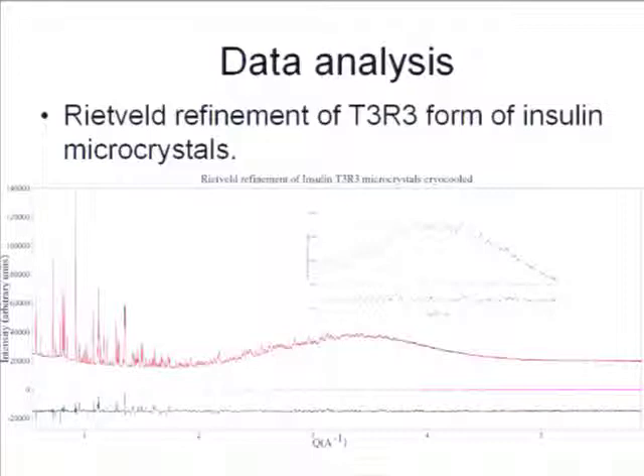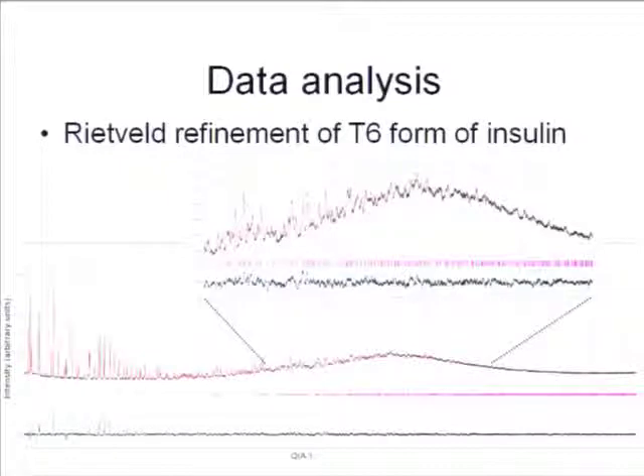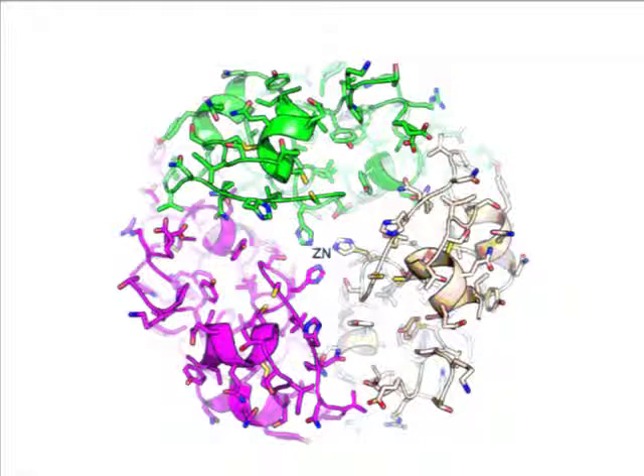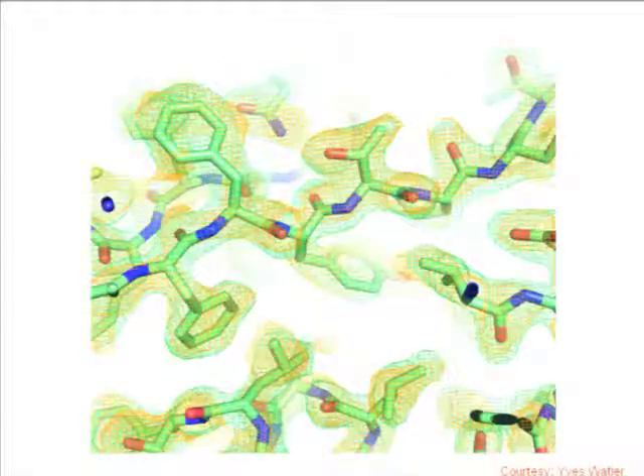4 angstroms to the -1 correspond to 1.5 angstroms in this spacing. And although the peaks at high 2 theta are very low in intensity, overlapped, and so on, they are still very important for the quality of the electron density maps. Here is the data set and the Rietveld refinement of the T6 form of insulin. And by using this data, we could really easily solve the hexameric polymorph of insulin, which looks like this. It has 6 protein chains around a zinc atom, and the zinc atom holds the polypeptide chains together. The electron density maps were very, very impressive coming out from this data.